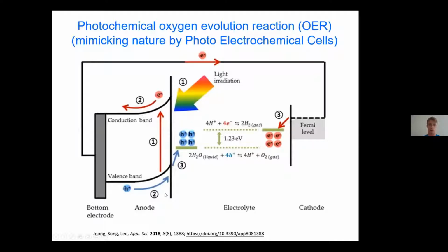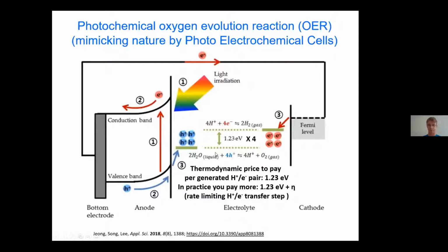So today we will mainly focus on the anode site and the electrochemical processes taking place on the anode side, on an electrocatalyst that is specific for oxygen evolution catalysis. There's a thermodynamic price you have to pay for each proton electron pair you generate. That is 1.23 electron volts. But in practice, these proton electron pairs are generated in different steps. And some of these steps simply cost more in energy. So then you pay a higher price, and that's called the overpotential, represented by eta.